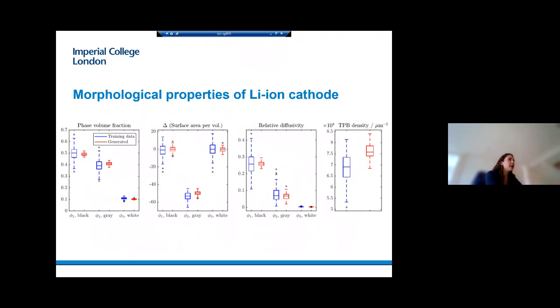So for the lithium-ion cathode, as you can see, we calculated the volume fraction, surface area, relative diffusivity, and the three-phase boundary density. And as you can see, the mean of the generated values and the mean of the training set are basically the same. And although we can see that the variability of the generated sample is lower than the training set, we can see that we generate unique samples that represent the training set.